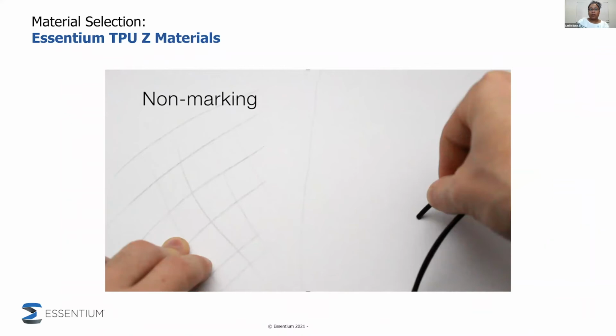If we take a look at the non-marking properties of this carbon nanotube coated material, it's great because say if you took a piece of paper and did some marking, you would not get any streaks on either paper or a printed circuit board. However, with competing materials, if we look at the section on the left, when rubbed onto a piece of paper, you do see marking, almost like working with a crayon or piece of charcoal. So that's definitely a very unique and rare property for extrusion-based 3D printing materials.